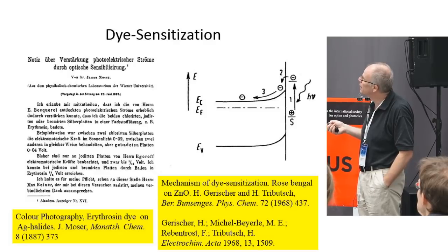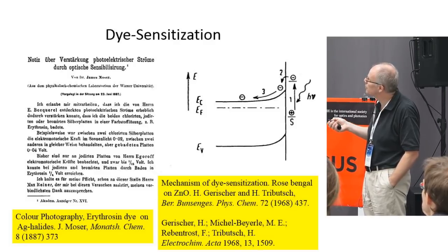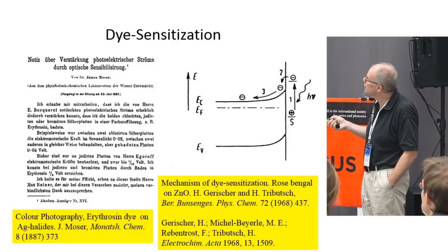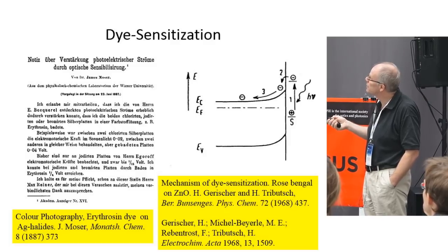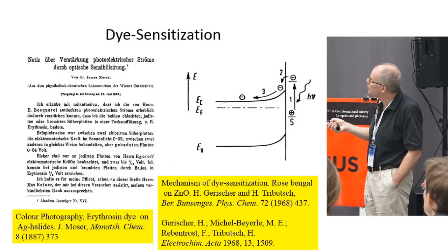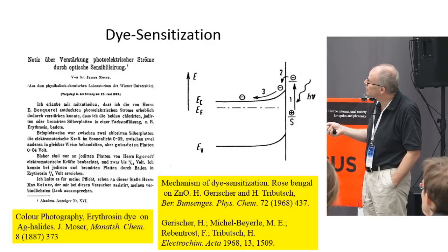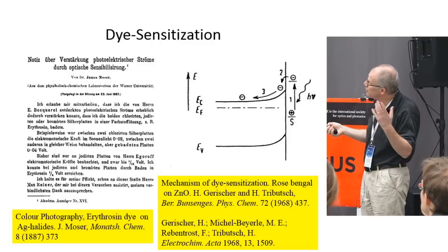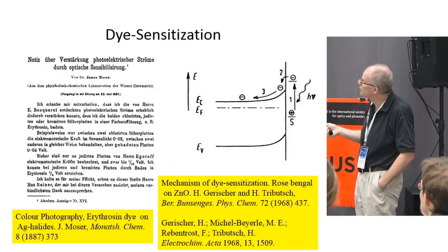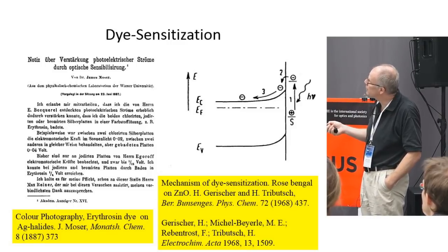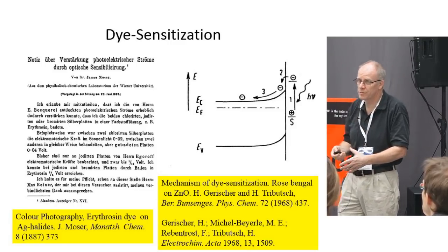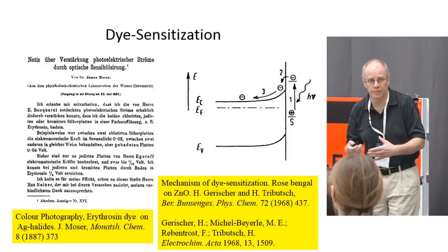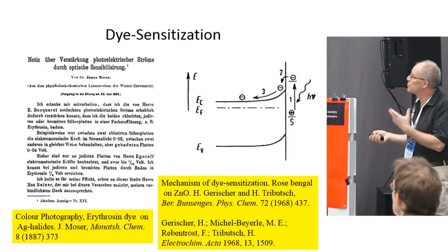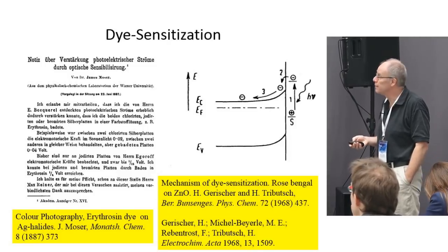So you have the dye adsorbed to the semiconductor surface. You excite the dye with an electron to the excited state, and then it's injected into the conduction band of the semiconductor where you can transfer it and collect it as a current. Then in the semiconductor you have a Fermi level, or in chemistry, electrochemical potential, and the difference of the Fermi level to the redox potential of the electrolyte makes the voltage of the solar cell. So that was explained in that time.